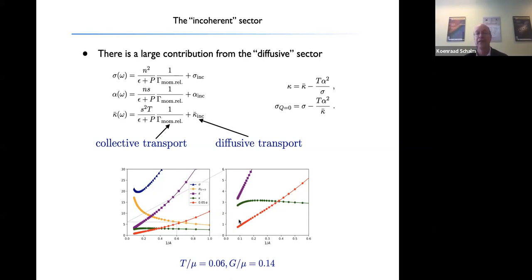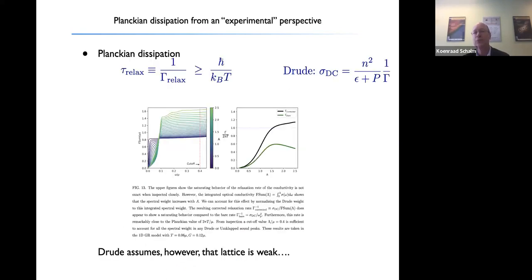And so this really means that the momentum now relaxes so fast that this collective part, this part where the whole fluid sloshes back and forth, becomes negligible. And the transport is dominated by this intrinsic diffusive term. There's one thing you should be a little bit careful about, because there's a naive way to always think of the DC transport in terms of this relaxation rate.